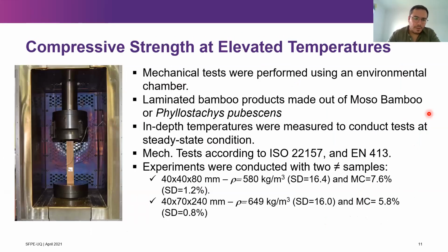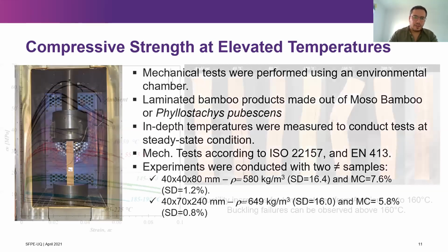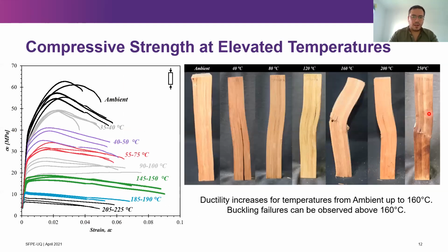So we started testing laminated bamboo in compression. We did the first tests on round bamboo, but we quickly realized that round bamboo loses strength very quickly. So for fire conditions, we definitely wanted bigger cross sections, and that's when we decided to put more attention on engineered bamboo products. We exposed laminated bamboo specimens in an environmental chamber where we could carefully control the temperature. We established correlations between surface temperature and internal temperature of our specimens, and we were able to understand the reduction in the compressive strength. We also measured the reduction in the modulus of elasticity, and we tried to recreate the stress-strain behavior of bamboo under compression.